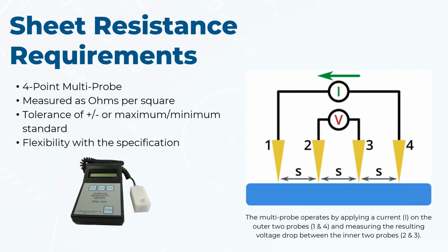So one of the final tests, this is mostly for indium tin oxide (ITO) coating, is sheet resistance. And this is measured with a 4-point probe. The measurement requirement that they give is ohms per square. And that's basically meaning that you have your multi-probe here, and probe 1 and probe 4 are at fixed positions. Probe 2 and probe 3 actually retract when they make contact with the coated surface. And as probe 2 and probe 3 touch down on the surface and complete the circuit, you get your sheet resistance requirement.